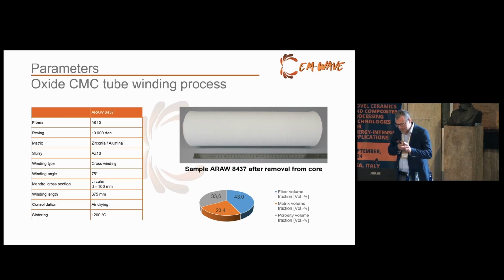And now I switch to the oxide CMC winding process. Again, we have a winding machine which takes the aluminum oxide fiber and winds the system on a core. And then at the end, after sintering at 1200 degrees C, you have this nice triple thing where your fiber volume is around 43%, your matrix volume 23%, and the porosity still is above 33%, but with a completely different microstructure than the silicon carbide fiber preform.